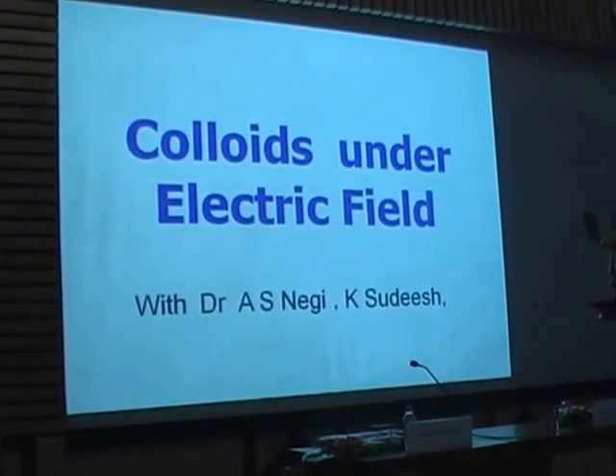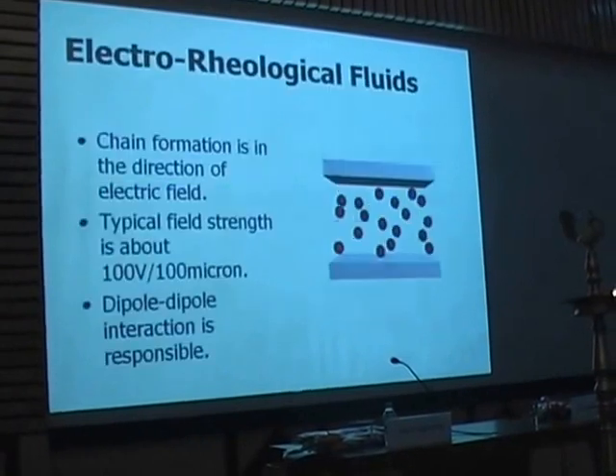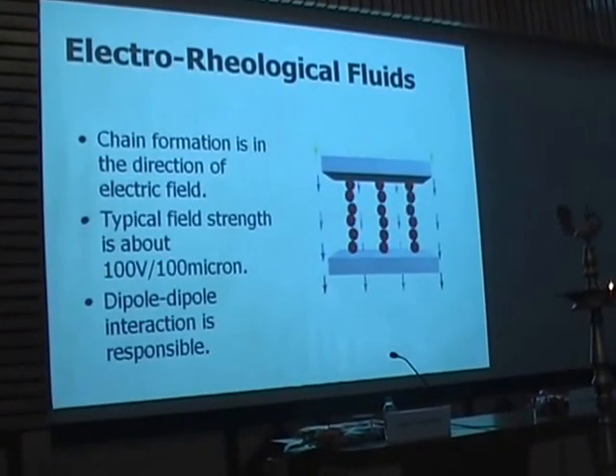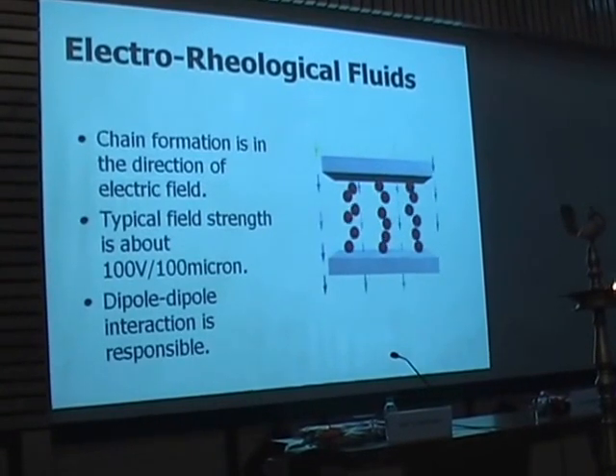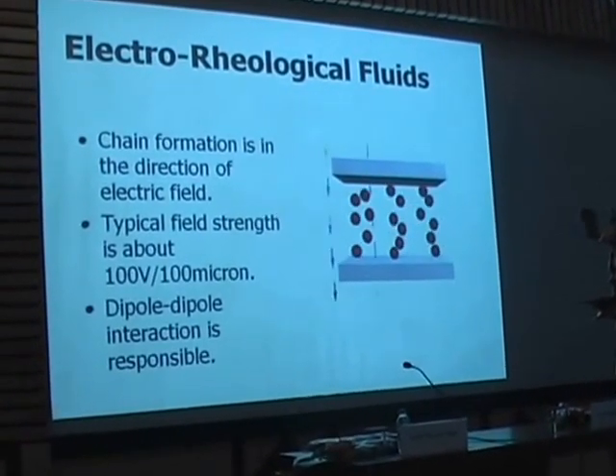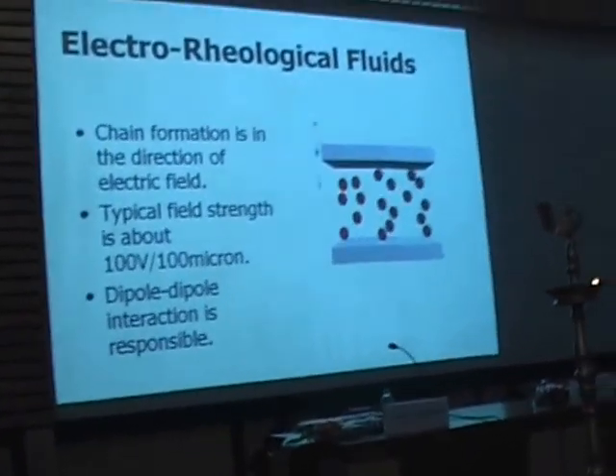Now what happens when you put colloids in an electric field? These are the colloidal particles in an electric field. It is a very simple experiment. You put electric field around this, put in colloidal particles and they form chains. This is called electro-rheological fluids, which has enormous applications in brakes and so on. You can apply brakes by putting on an electric field. This is something well known. What is less known is the next slide. It was discovered 10 years back that if you apply the electric field in this direction, the particles come together in this xy direction, which is unusual, not along the field but perpendicular to the field. That was not known, which means the particles are going to feel each other when you apply an electric field.